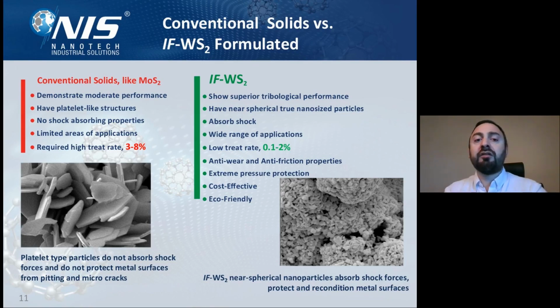There are also limited areas of applications, primarily in greases, in coatings, and some in polymers. And it's primarily supplied in a powder form. The required treat rate is 3 to 8%. However, IF-WS2, due to its size, has a much lower treat rate, between 0.1 and 2%.